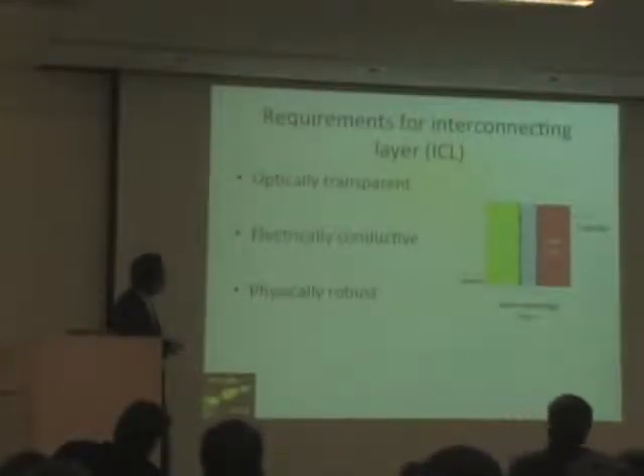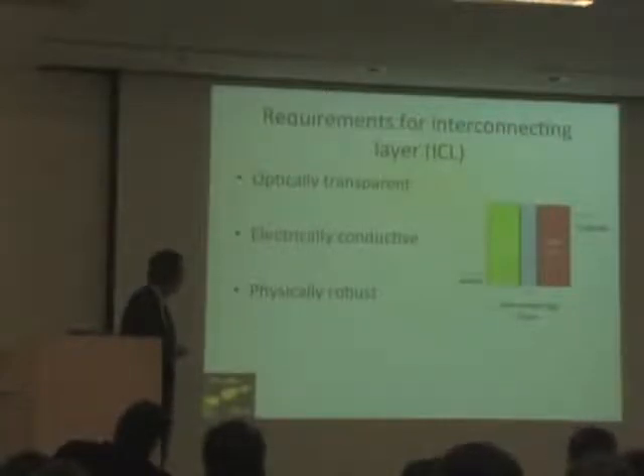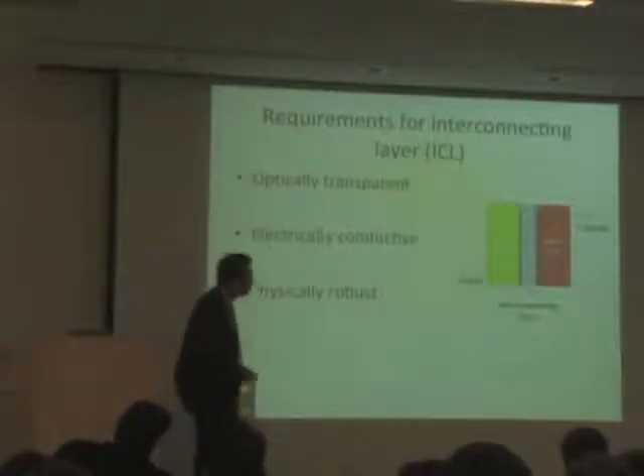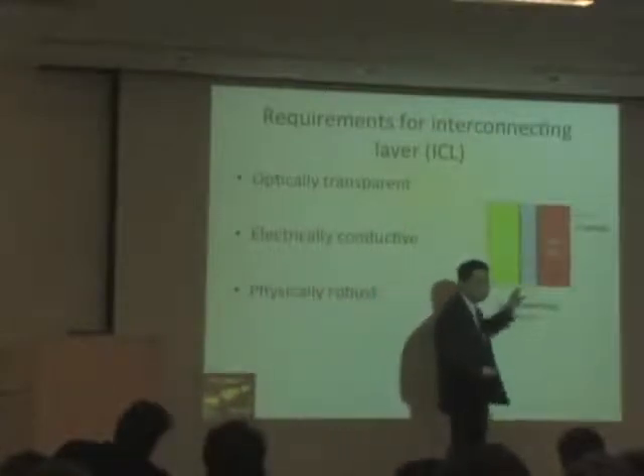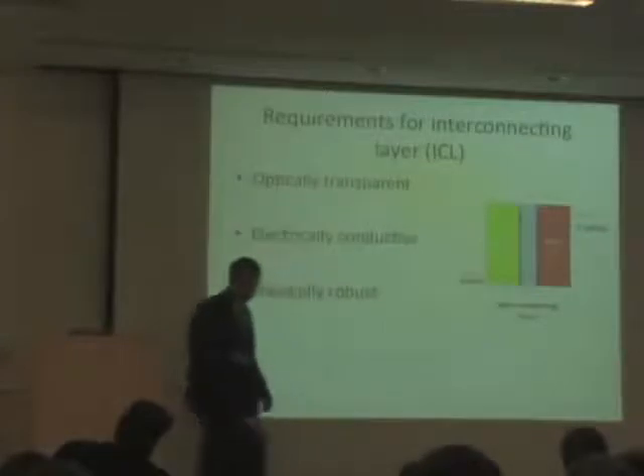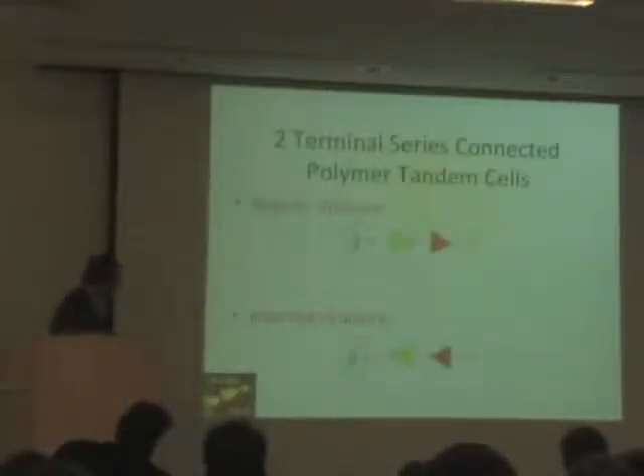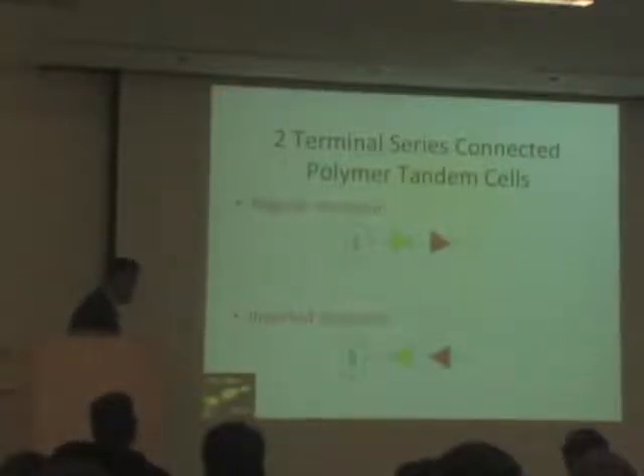So the interconnecting layer must be optically transparent. You don't want to pay any toll in this interconnecting layer. It must be electrically conductive and physically robust. Why is it important to be robust? Because we are using solution processing. Every layer we talk about today will be solution processed and coated, except the electrode. So that's why you need to be physically robust. And then here's a regular structure where we define ITO as the positive contact, and this is the inverted structure, where ITO is the negative contact. In principle, the regular structure is the current structure a lot of people publish, but the inverted structure, to the best of my knowledge, is what the industry uses to produce their solar cells because it's more stable.